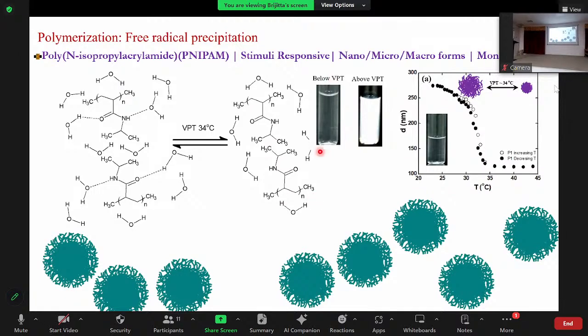I said, like when you have a dilute suspension and when it crosses 34 degrees, it becomes turbid. It is only a physical phenomenon, but how do you quantify it? So here I am showing you an experimental plot where we have taken nanogels whose size is around 273 nanometers at 20 degrees. And then when you increase the temperature gradually, the size actually decreases. And at this junction, you see that there is a sharp fall, and this fall is what we identify as the volume phase transition temperature. This is the temperature at which the hydrogen bond breaks and the isopropyl groups come in close proximity.